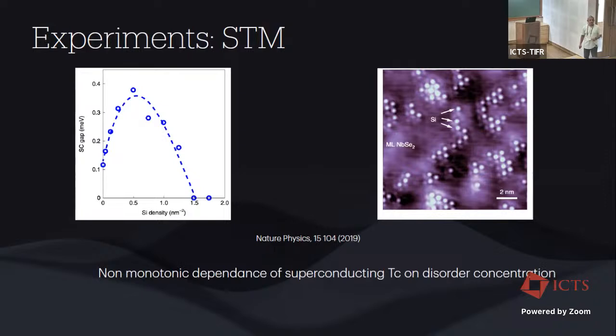Is that an average of the gap? Do they have any homogeneity because the sample is quite disordered? Yeah. So they are essentially looking at the average of the gap over the sample, considering it to be proportional to what is suppressing the TC in the system, and then looking at it. Okay. So yeah. Thank you. So it's a non-magnetic impurity. So the expectation is that in an effective Abrikosov-Gorkov theory, that is what is contributing.